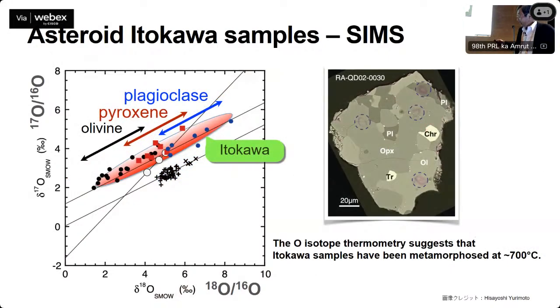So we recognize there is a variation. The plagioclase, blue, is plotted in this region. Olivine, black, is plotted here. And pyroxene, red, is plotted in this region. This variation corresponds to the formation temperature of these minerals. So from this variation, we can estimate the formation temperature. And the temperature is calculated to be 700 degrees.